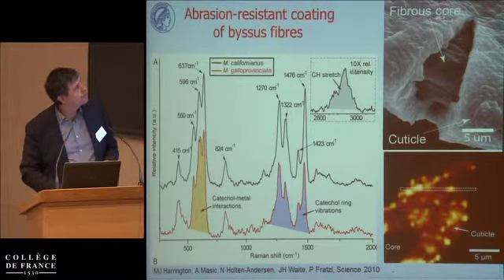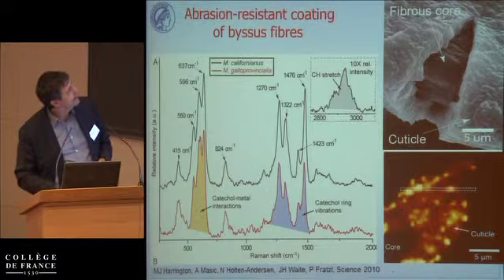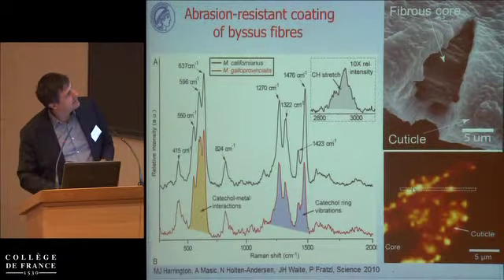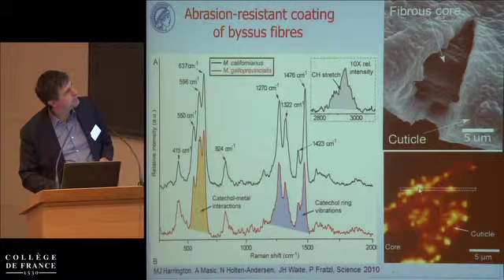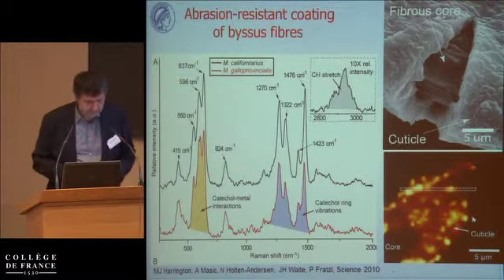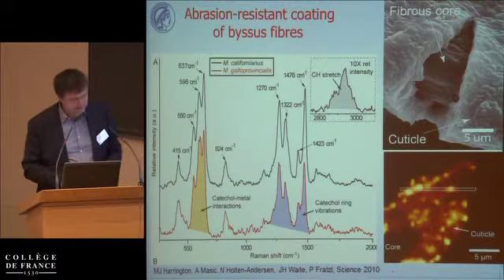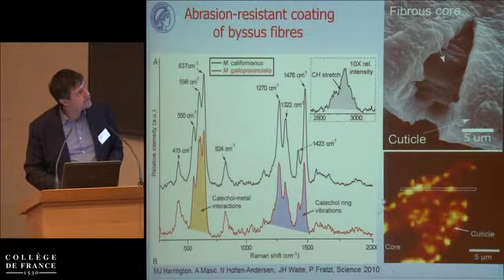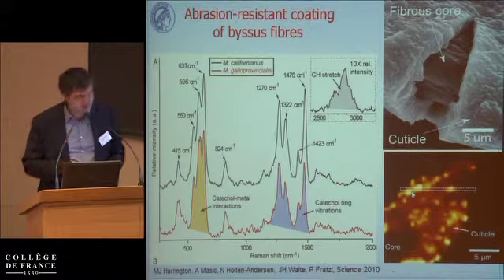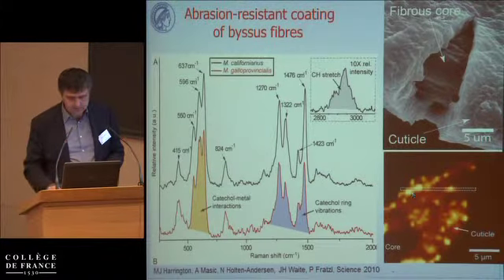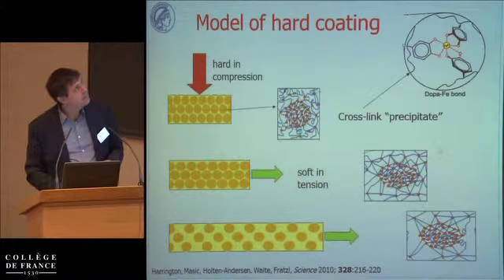Well, here is the solution found by the mussel. Never mind these pictures here. This is Raman spectroscopy, confocal Raman imaging. And you see these bright spots here that look like precipitates. Well, they actually are precipitates, but not of another material. This is just the cross-link density. And now the cross-links are just another version of metal coordination bonds, namely these bonds here.